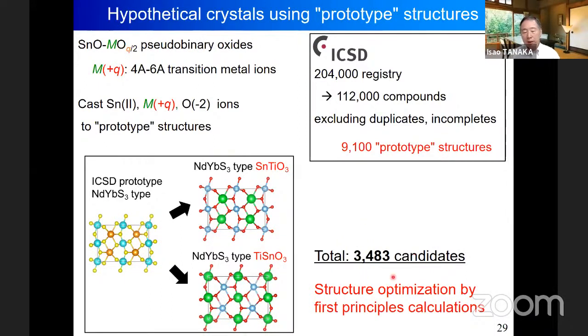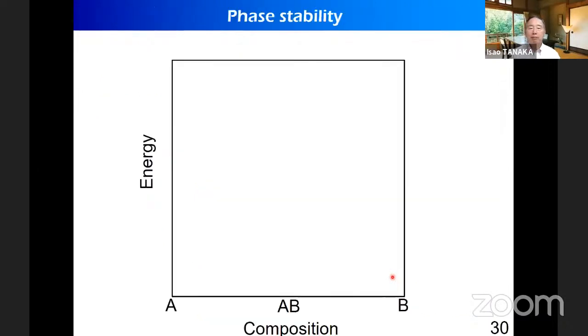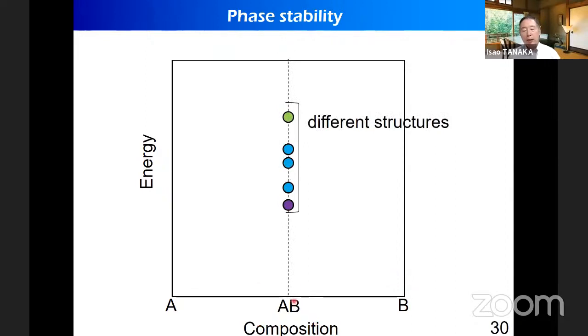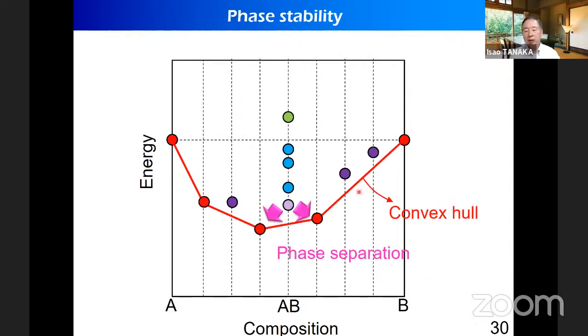So altogether, the number of calculations is something like 3,400. We examined thermodynamical phase stability, which means for the compound AB with different structures, you can find this violet one is the lowest energy. It does not mean that this is thermodynamically stable, because you have to look at the whole phase diagram. And if the convex hull is drawn like this, then you can immediately find that this is not a thermodynamically stable compound anymore.